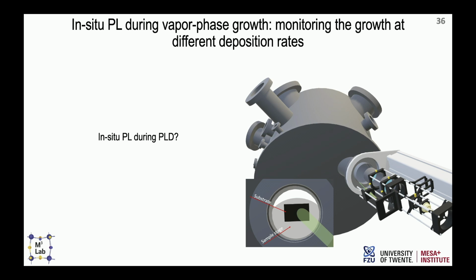So we can actually install the PL, do it from the window at the bottom, as shown here. And then you look at your substrate during the deposition. So it's a good way to see what is happening if I change the deposition rate, and then you can screen very quickly if something bad is happening.